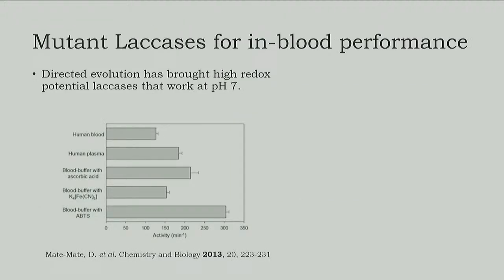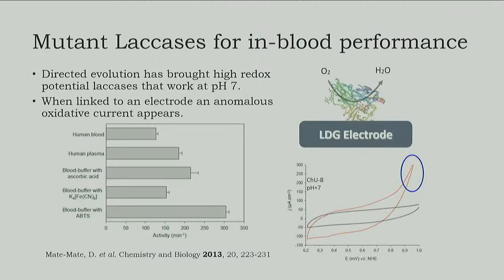Okay, so we could see that this enzyme, in different biological fluids like human blood or plasma, or ascorbic acid, was keeping pretty much of its activity. This one is a mimicking buffer with a mediator. So the activity is not zero, it's larger than zero. This is what we were looking for, and in this way it was a serendipity moment, because we were working at neutral pH, because of course we're going to make physiological conditions, so then we changed the working conditions.